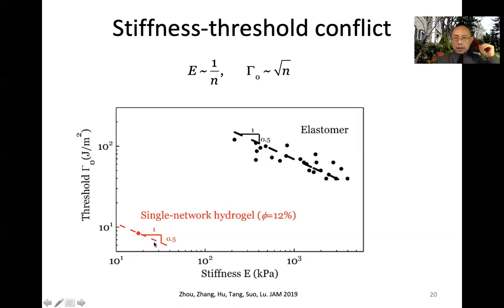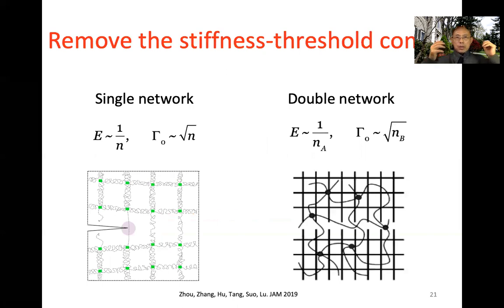Now, suppose we do the following. We make a double network hydrogel. Since Jianping Gong made this gel almost 20 years ago, many people have studied the properties of double network hydrogel. Our group pushed this, and we started to study the fatigue of this double network hydrogel. Here's our conclusion.